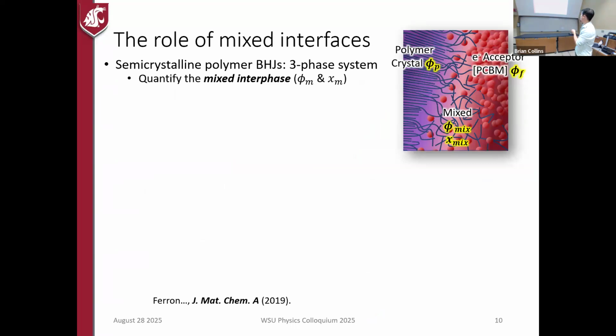And so what we're going to do is parameterize this blend as a three-phase system, where we have a polymer crystal phase, an aggregated acceptor phase. These are fullerenes, which is why I made them balls. And then a mixed interface between the two, characterized by its volume fraction and composition concentration in the mixed phase. And so you can see we basically have, well, four, but really three independent parameters for this model. And so we need three measurements.